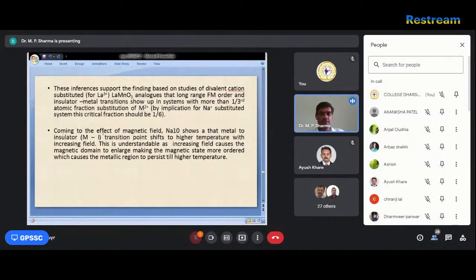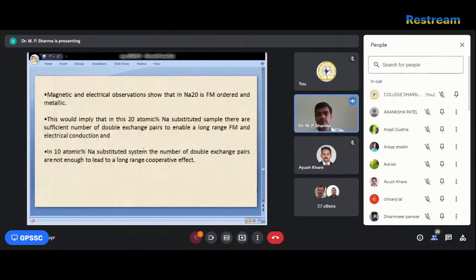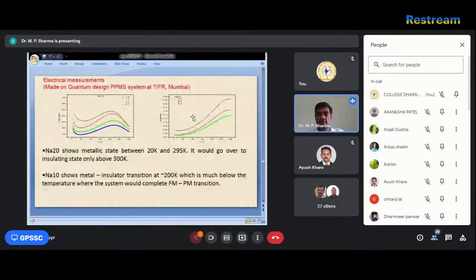So this is coming to the effect of the magnetic field. The sodium 10 shows a metal to insulator transition. The points shift to the high temperature with increasing field. This is understandable. Increasing the field causes the magnetic domains to enlarge and makes the magnetic state more ordered, which is the metallic region, at the higher temperature. So if you look at the measurement, in both the cases, 0.1 and 0.2, one is increasing the TC.